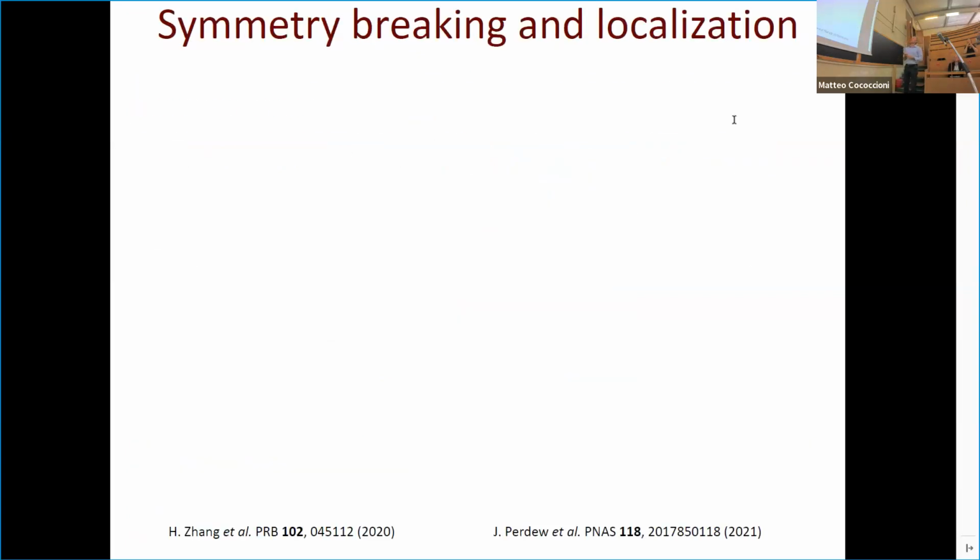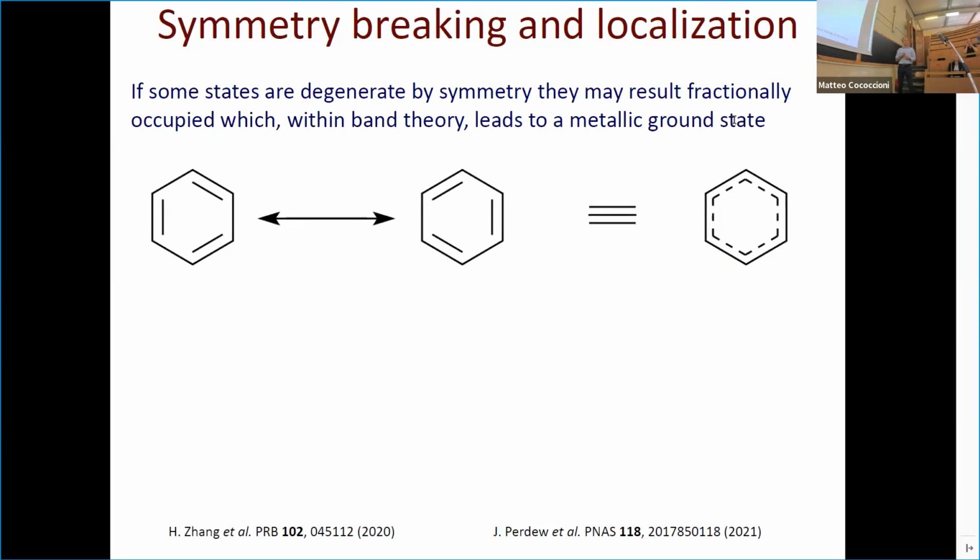Okay, so what I just mentioned turns out to be possible if symmetry allows. Okay, so in the cases that we've been looking at previously, the ones pertaining to the family of battery materials, we were sort of lucky because the lithium in the structure basically breaks the symmetry. Okay, you have lower symmetry just because lithium is occupying a fraction of the possible sites that it can occupy.